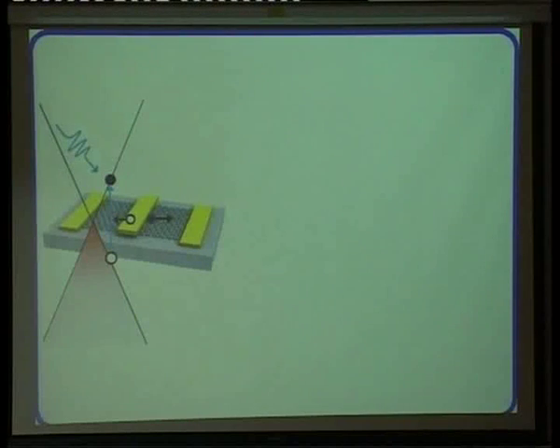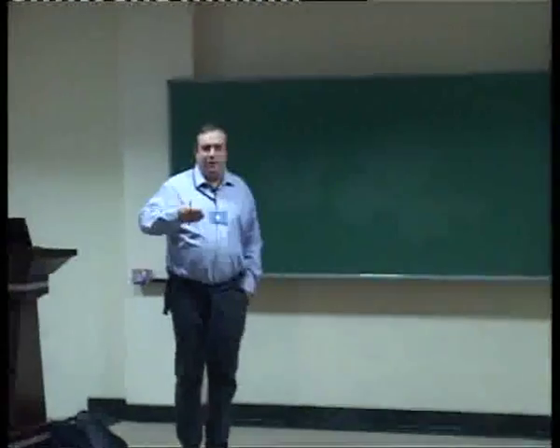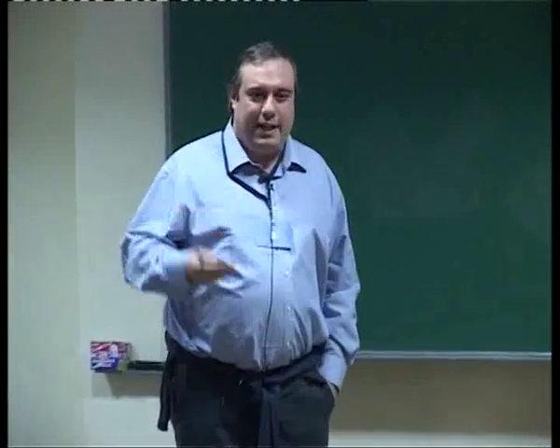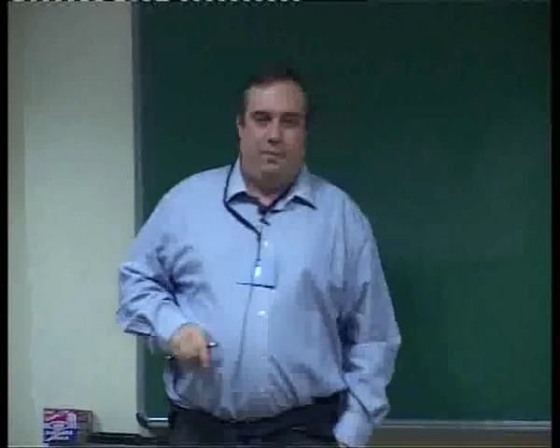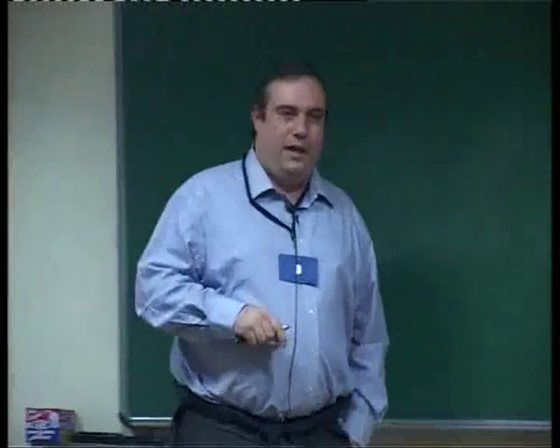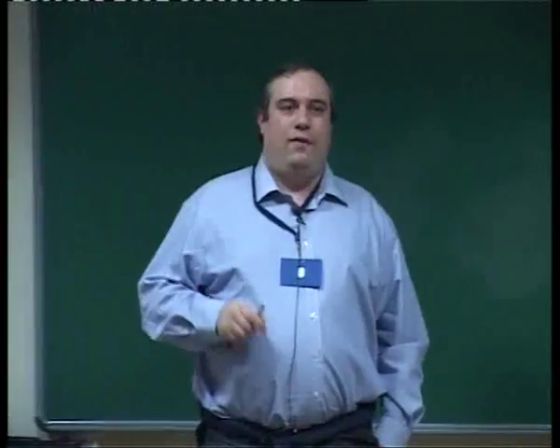That's only true for undoped. That's only for undoped graphene, but when we speak about light, we don't care about the doping, because we are speaking about 5 millielectron volts, maybe 300 millielectron volts, and the sun and everything else is much higher. There is only one frequency where there is a problem, terahertz, and very low frequency.